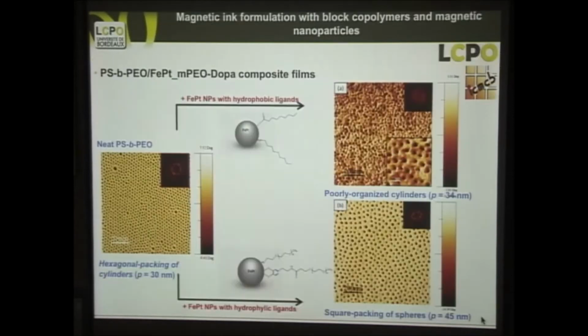But what's next? Once you have the particles, we used the same kind of technology that I just showed you. We used block copolymers that can organize in cylindrical structures, and by modifying the surface of the particle with hydrophobic tails or hydrophilic tails, we can direct them to go to the one phase or the other phase.